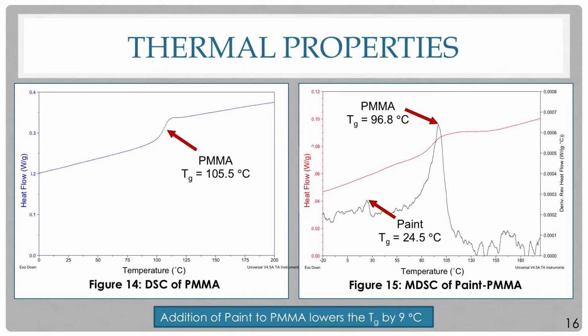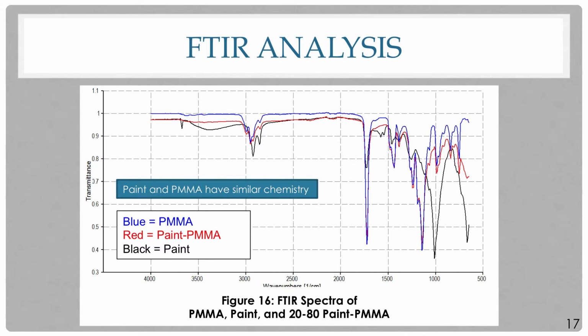The FTIR results of latex paint and PMMA showed that they had similar bonding, which makes them a good candidate for forming an miscible polymer blend. Secondly, you'll see that the red line is the paint PMMA, and it has characteristics from both of the original materials, latex paint and PMMA, which shows we did in fact achieve an miscible polymer blend.